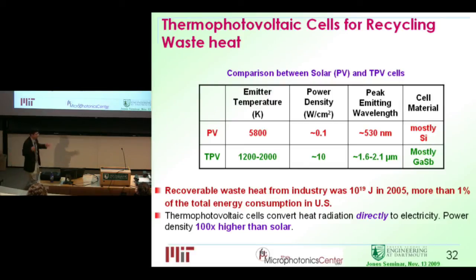And the reason is not because you have a heat source hotter than the sun. It's actually because you get so close to it. So you can get a power density of about 10 watts per square centimeter. So using a similar device as solar cells, but with a smaller bandgap material for the infrared regime, we can convert heat radiation directly to electricity. And this power density can be 100 times higher than solar cells.